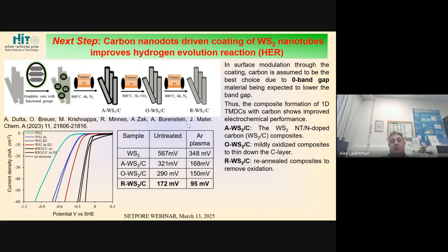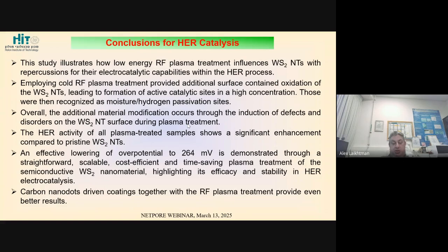Now we are just preparing the paper, so I'm not going into much detail about this process and the mechanism, but the results are very promising and quite exciting. So I would like to briefly summarize this part of my talk. We illustrated that low energy RF plasma treatment indeed improves the catalytic properties of WS2 nanotubes, and with the carbon nanodot coating we obtain results which are very close to platinum electrodes, but hopefully with much lower cost and quite high stability. So we consider that the mechanisms are related to pores and defects produced by the plasma that serve as active sites for the reaction. So this is about this type of research.